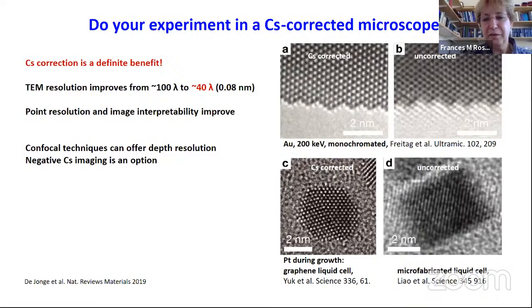Okay, so having said that, if you get the chance to do liquid cell microscopy, you still want to pick the best microscope you can. Definitely do your experiment in a modern aberration-corrected microscope, because aberration correction, although you tend to think of it as a way to improve the ultimate performance of the microscope, it also is a way to improve the interpretability of the images. And if I compare these two images, you can see that they both show where the atoms are in this random sample. But look at these edge effects in an uncorrected microscope, conventional imaging. The only way to really work out where the sample ends is to do a simulation. If you have a CS corrected microscope, you get much easier images to interpret. This is a vacuum experiment, but it's the same thing in liquid. This kind of fuzziness around the edge of the particles is caused by the aberrations. And if you can correct the aberrations, you get much easier images to interpret.